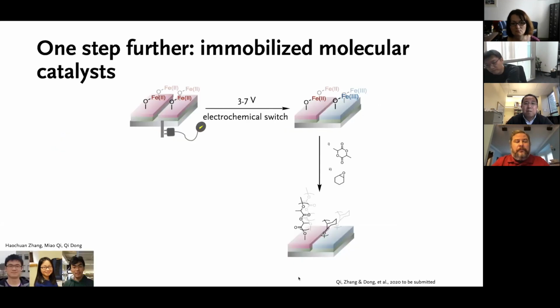So the next step is where I link everything I presented today together, right? So that's where my long-term interest as well is to try to immobilize molecular catalysts with a solid surface. There are a number of advantages of doing so. For instance, one thing we can envision is that you can immediately imagine you can form patterns. This pattern is only limited by the size of today's fabrication. The last time I checked, the commercial success is already at 5 nanometers.